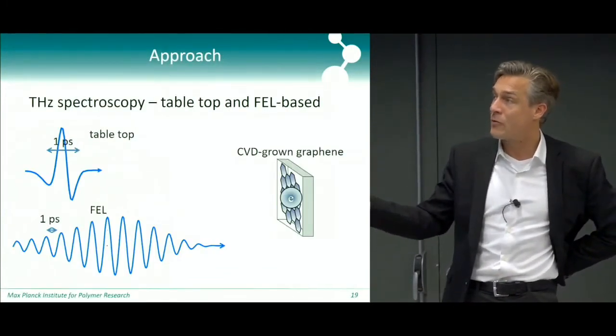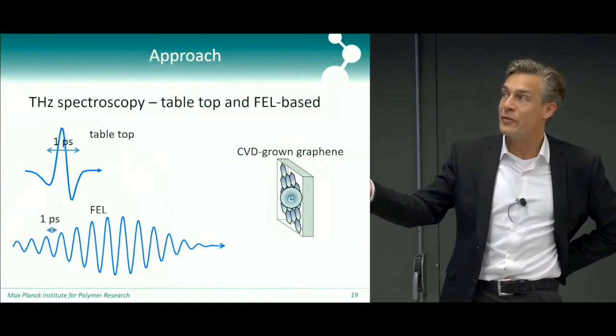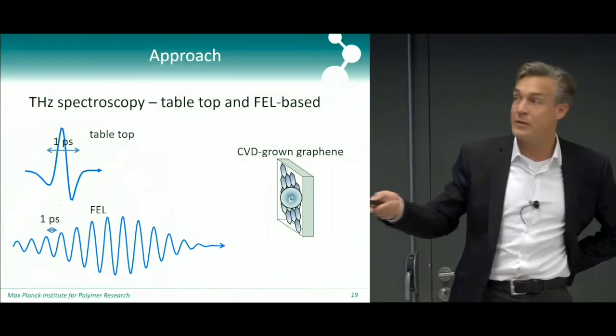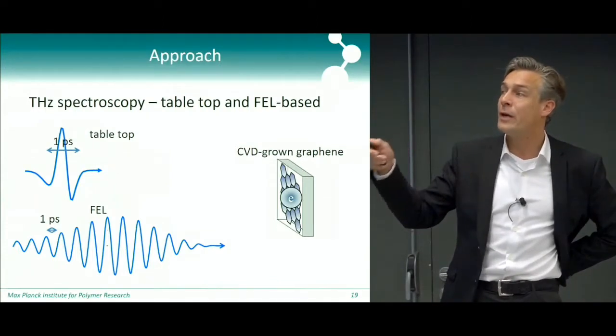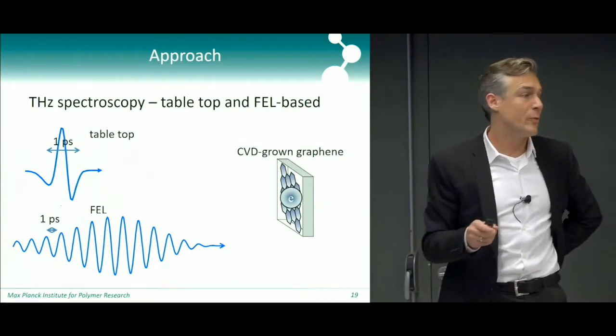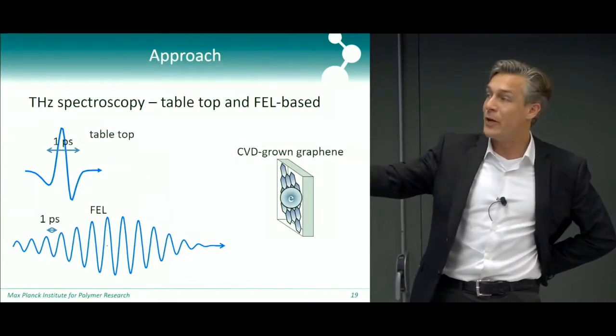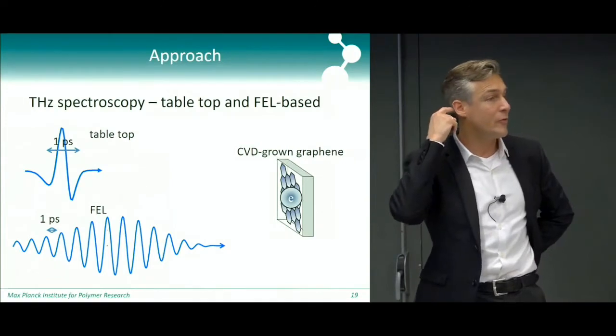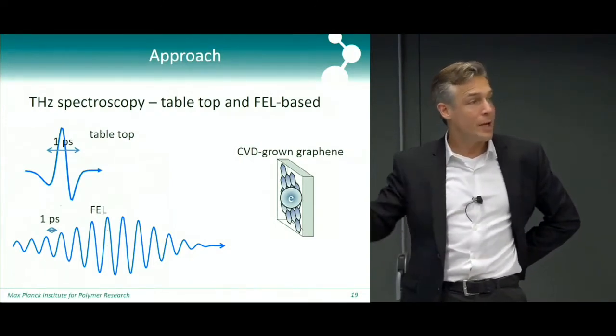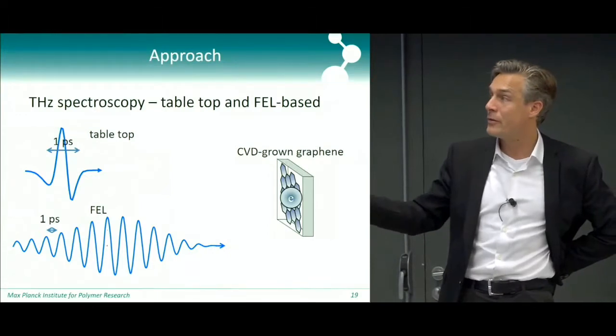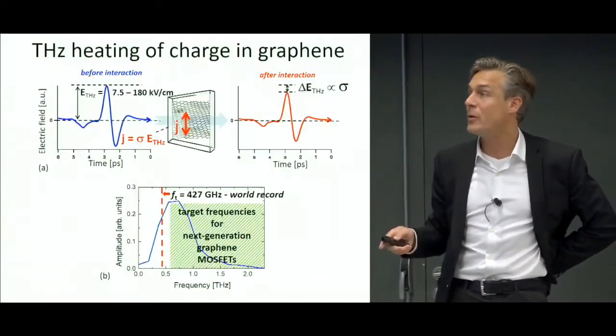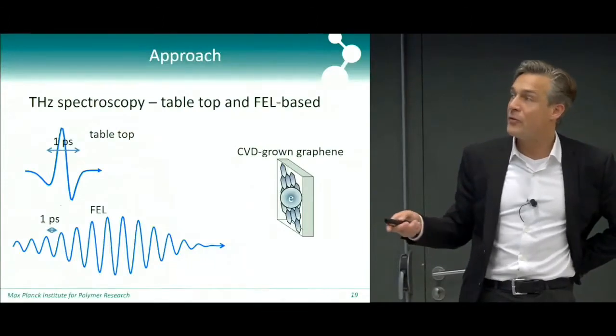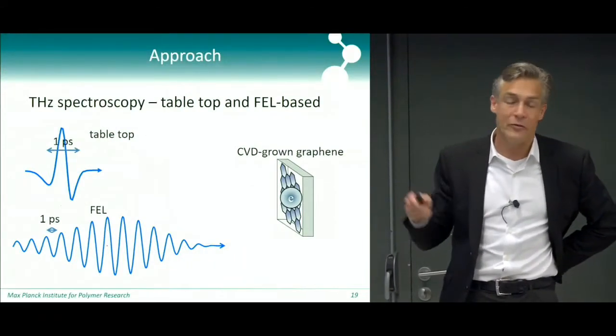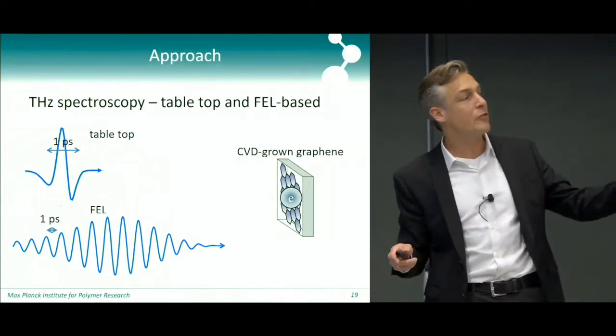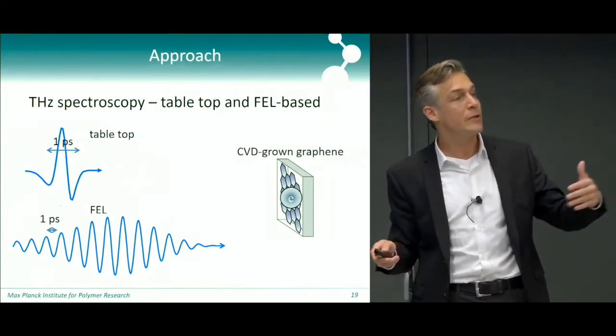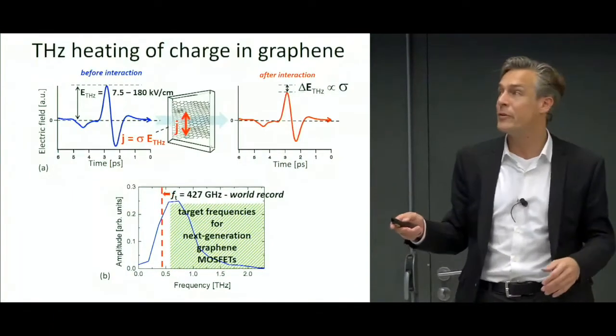We're going to take CVD-grown graphene, and we're going to look at the transmission of a tabletop terahertz pulse, which has this single cycle that I showed you before. And we're going to look at the transmission of a pulse from a free electron laser, which has a better defined frequency because it has many more cycles of the field, so it's a more narrowband pulse. And we're going to see how that affects the electrons and how the electrons affect the optical response. The first experiment is to transmit this tabletop pulse, increase the field strength, and see how that affects the conductivity of the material.